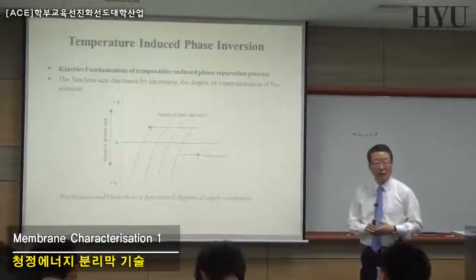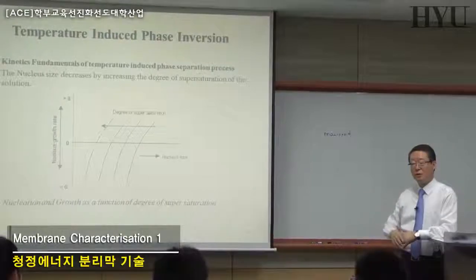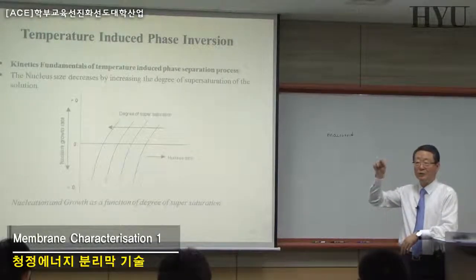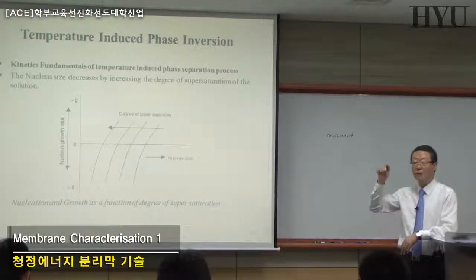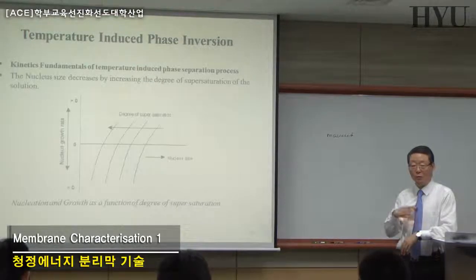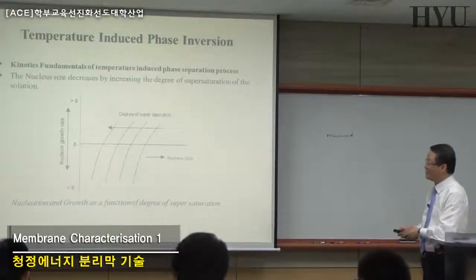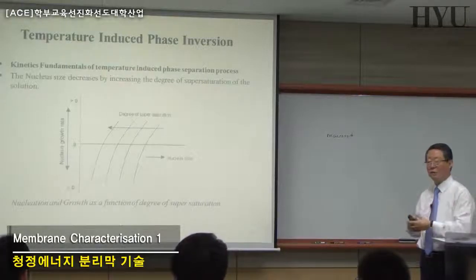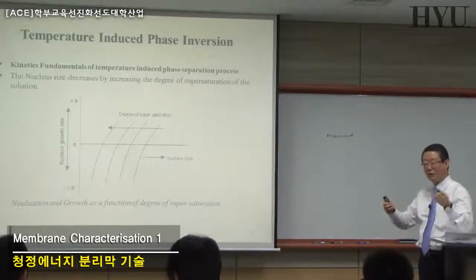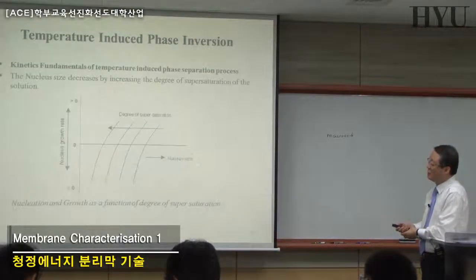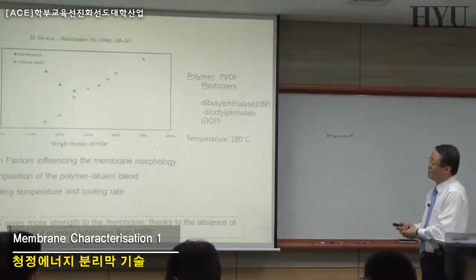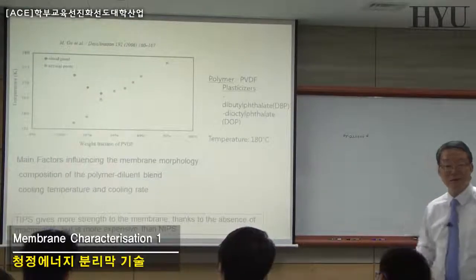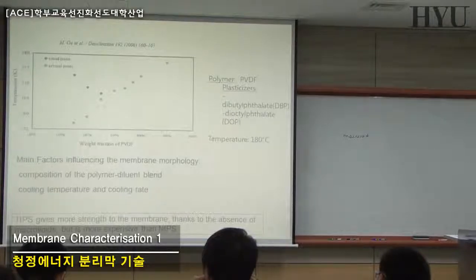In making the membrane, because this is the TIPS process, you start to have your crystal initiation or nucleation and then growth, so there are some other kinetic factors other than the thermodynamic factor that we have just described. The size of these nuclei could influence the size of your polymer structure and mechanical strength and everything. So the polymer solution and crystal size depend upon the rate of your nucleation. This is the typical and practical phase diagram in the case of making your polymer membrane. This is an example of PVDF, polyvinylidene fluoride, with polymer concentration from 0 to about, let's say, 60%, and the y-axis is the temperature.